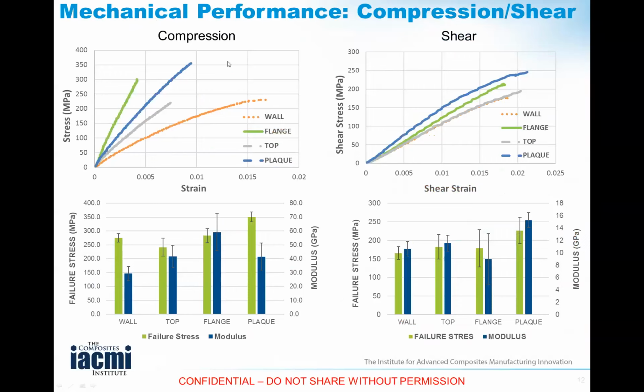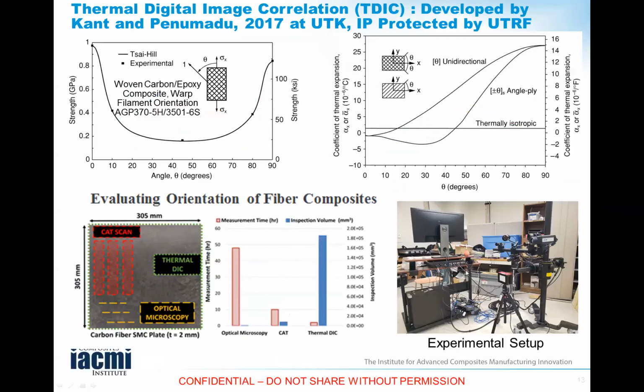We have done similar studies in compression and shear, and shear seems to be least affected by the orientation, but compression and tension have large effects. So in the last part, what I would like to quickly conclude is that we have developed a new technique called thermal digital image correlation at the University of Tennessee. This IP is being protected by our University of Tennessee Research Foundation, but I want to quickly introduce that to you.